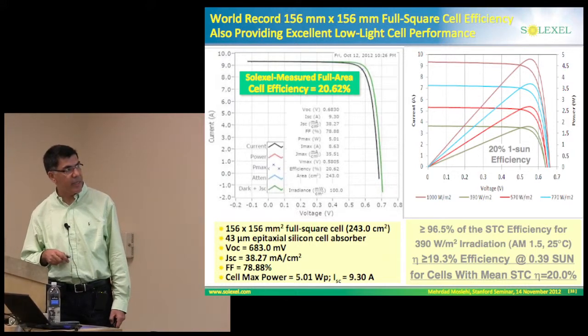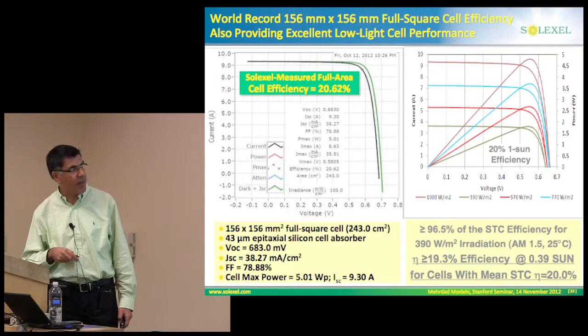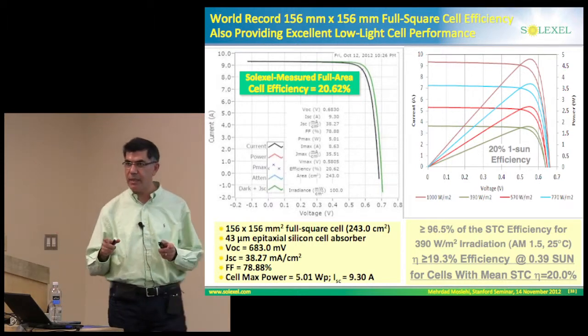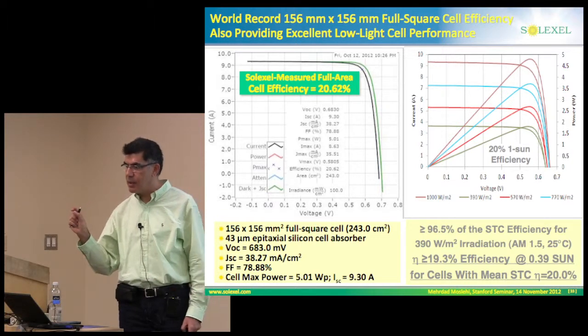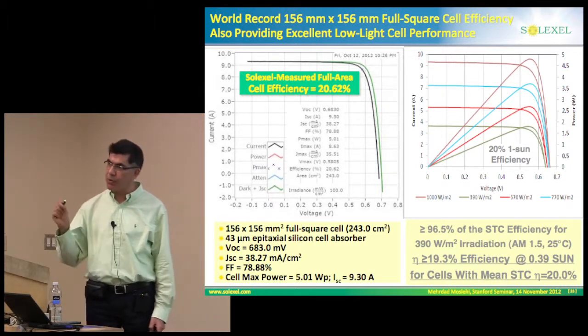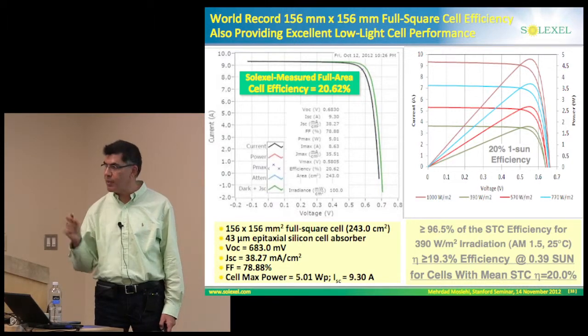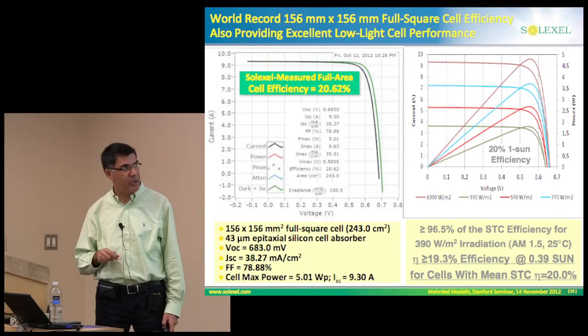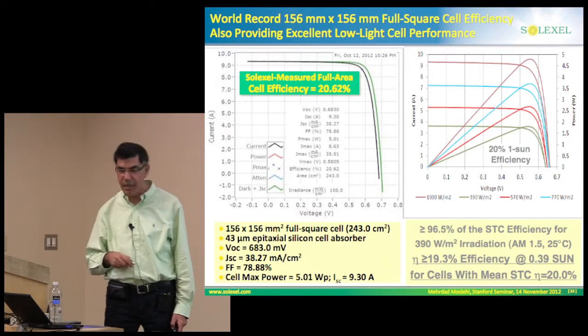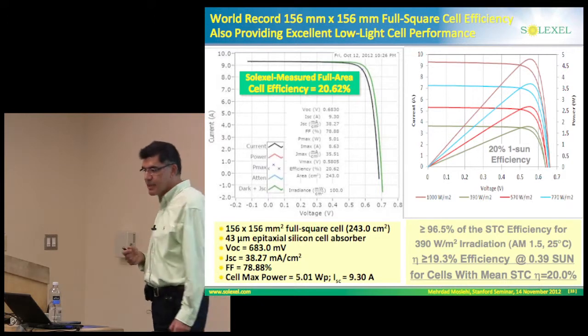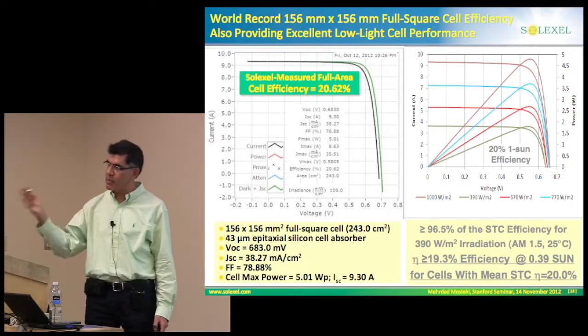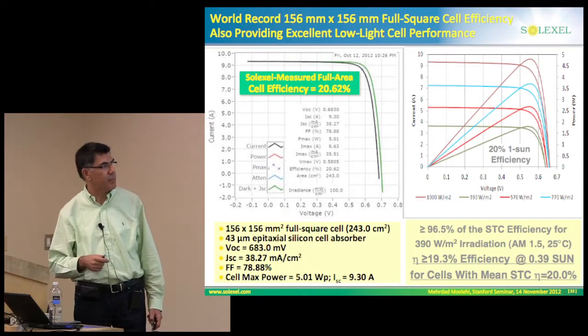It's also interesting to look at the low light performance. Now, this is a champion. The mean efficiency in our line is 20% with a very tight distribution, most recently about plus minus 0.4%. So if you take a cell from our mean efficiency bin, 20% at 1 sun, and then measure the efficiency at, for instance, about 0.4 sun, we get, with the STC efficiency of 20%, reduced light efficiency under this condition of over 19.3%. So this represents a pretty good low light performance that's important for energy yield of the panels.